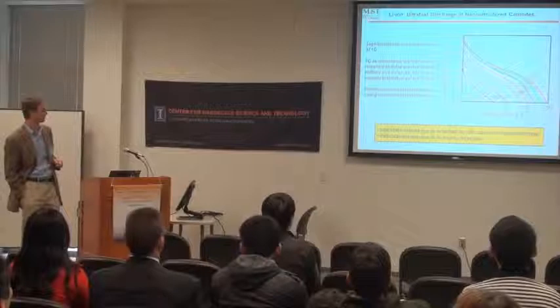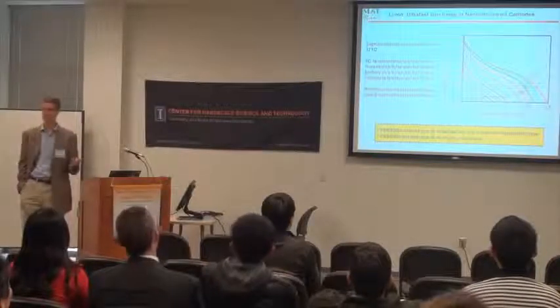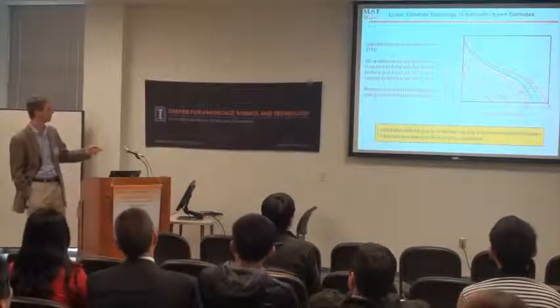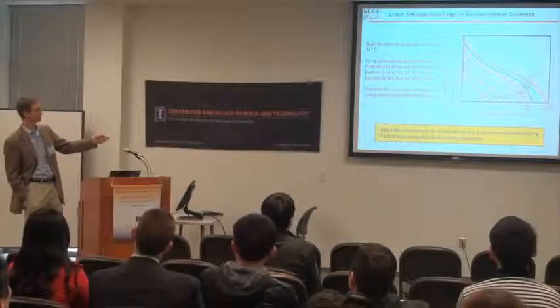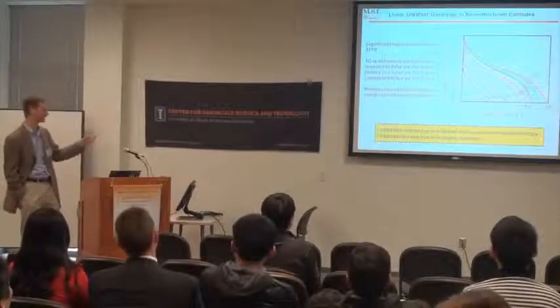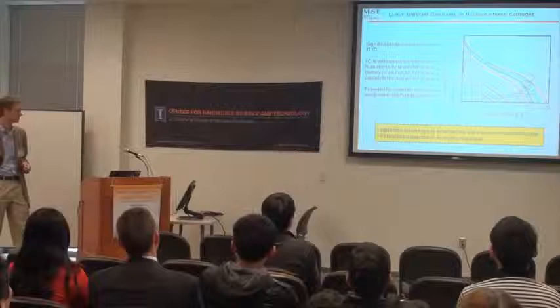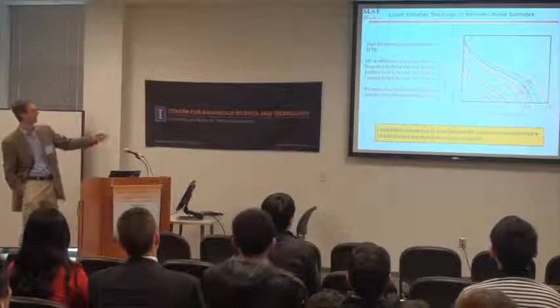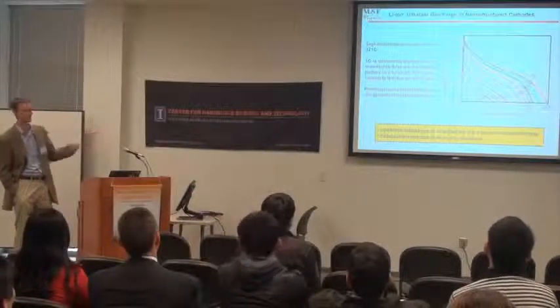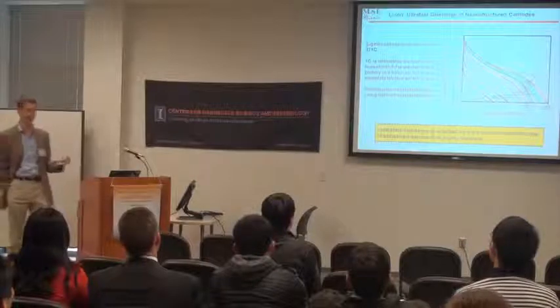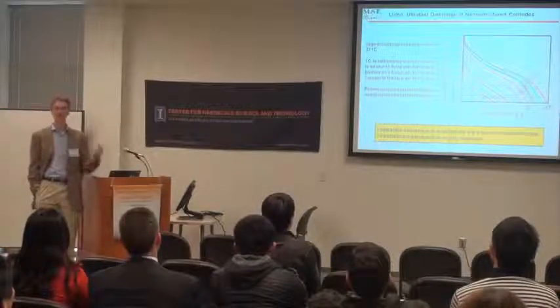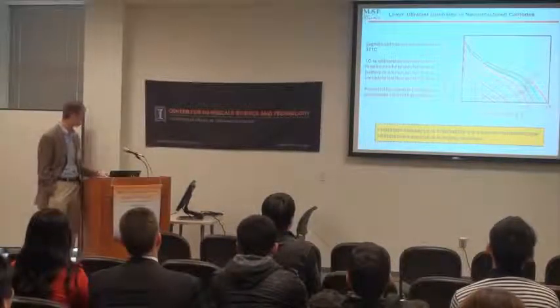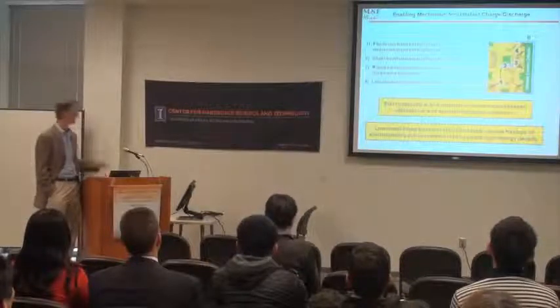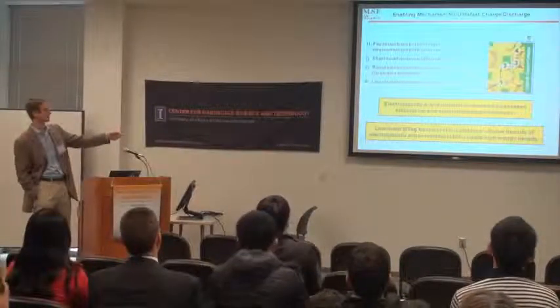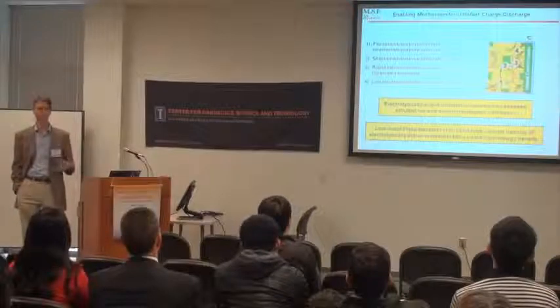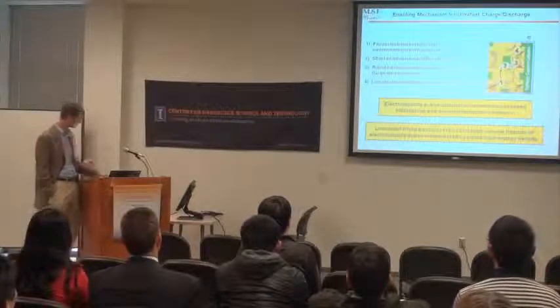We also did this in lithium-ion systems, which of course is perhaps more technically relevant today, and we see similar results. The discharge curve isn't as flat. I'd be happy to discuss those details over lunch if people are interested. But again, if you do a 10-second discharge, you get about 75% of the energy out. So very high charge and discharge characteristics. And again, that's because of the efficient pathways for moving what's important, electrons and ions.